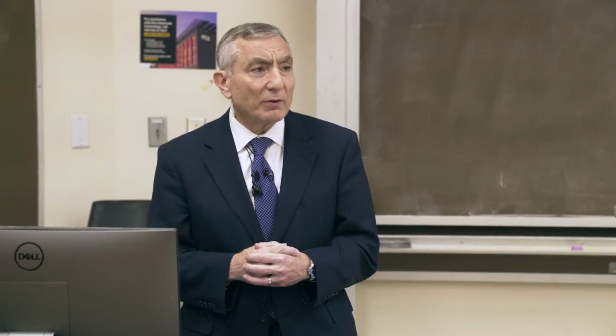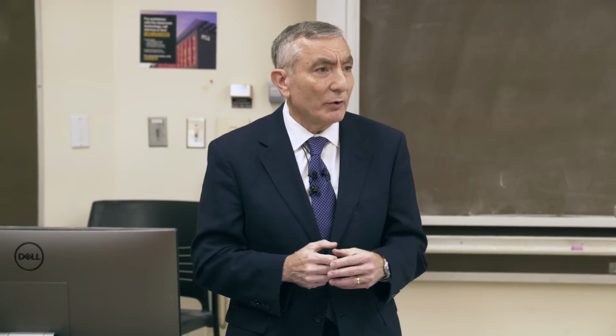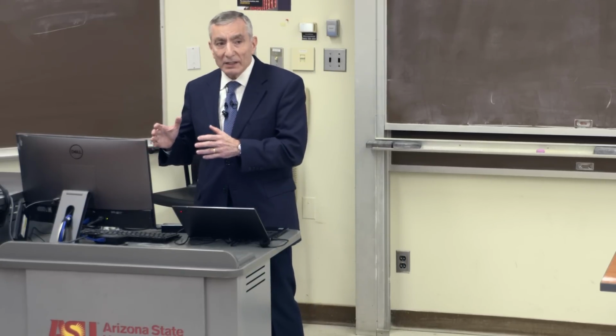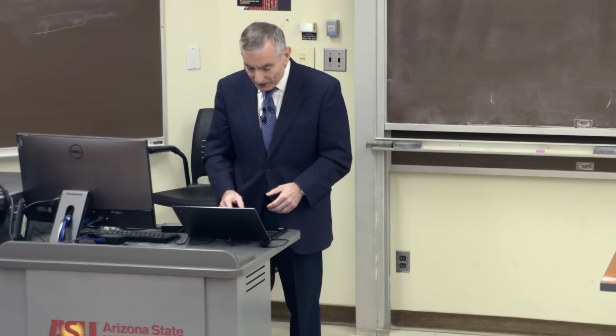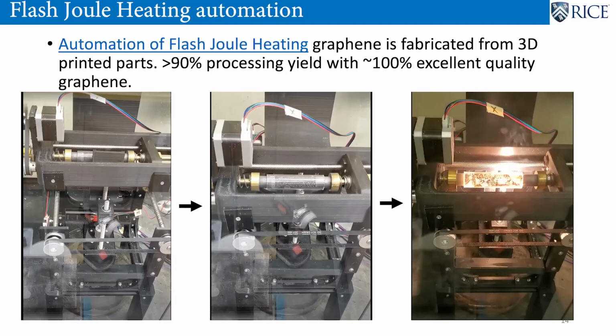And so what we could do ultimately from this, because we had gotten a grant from the Department of Energy just before COVID in 2019, October. And we had to deliver within 2 years. We had to take a U.S. coal product and make 1 kilogram in a day of graphene from that coal product. And so with this automated system, we were able to do that. And in fact, we could make the 1 kilogram in an hour and a half, where these just roll in, it flashes, and then it drops out the bottom, and another one charged would already roll in. So that was the automated system that we built.